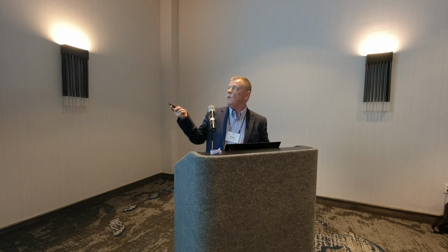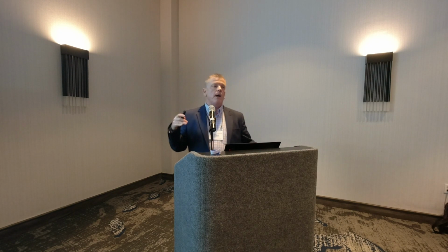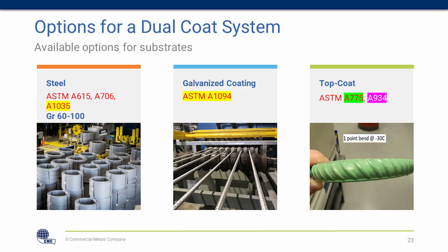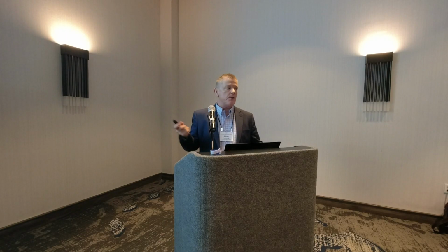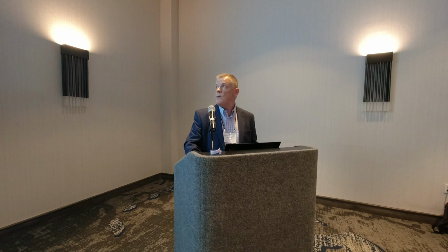for top coat with either 775 or 934, and then ASTM 1035 or the Chromex, either in any of the standards they have in the ASTM standard that you can apply a galvanized coating on top of that. And that's going to give you well over 100 years of service life and compete with anything that you might consider using stainless steel on.